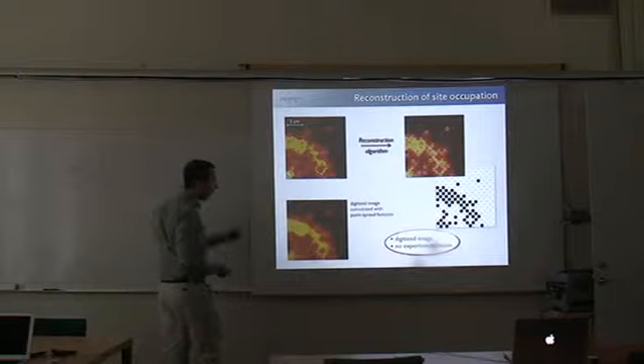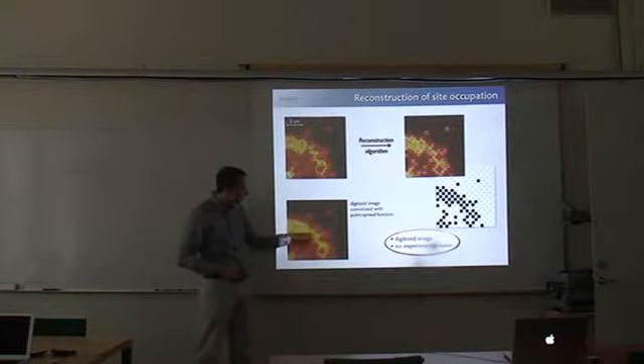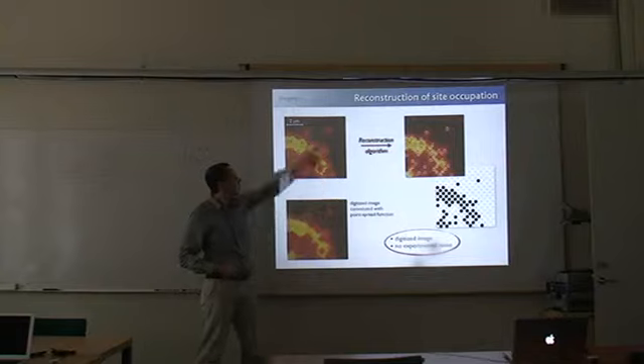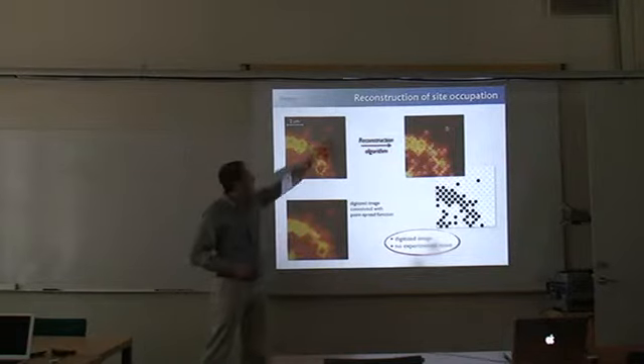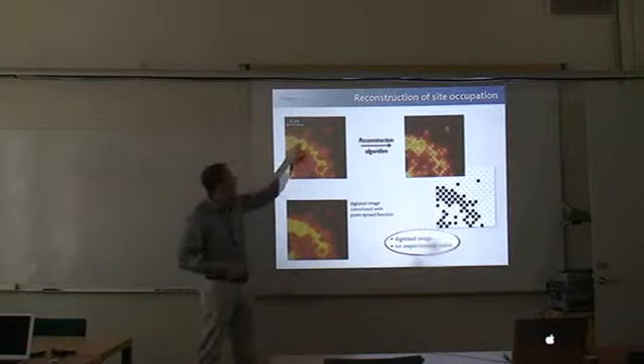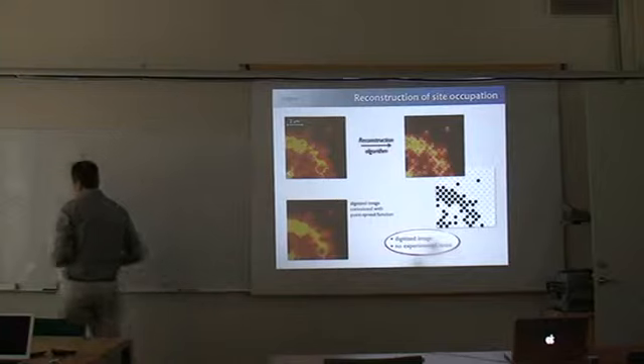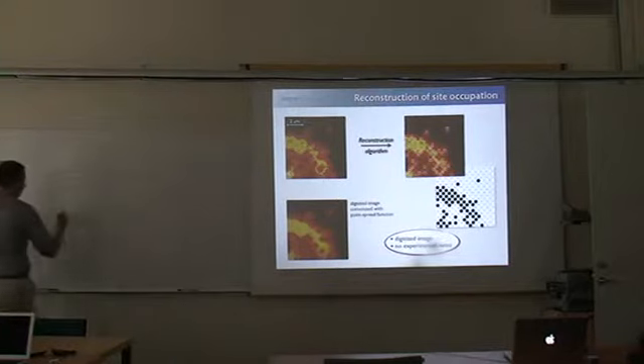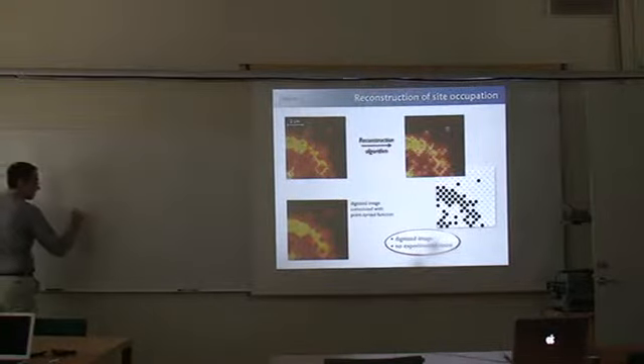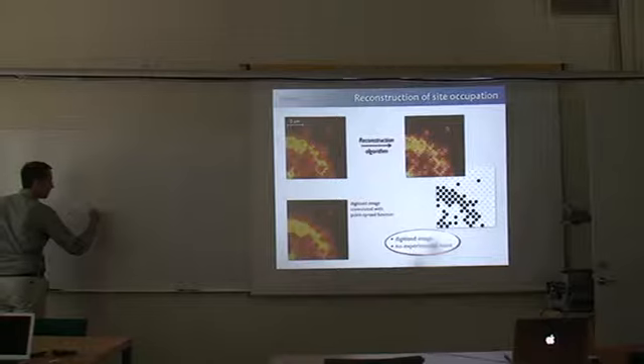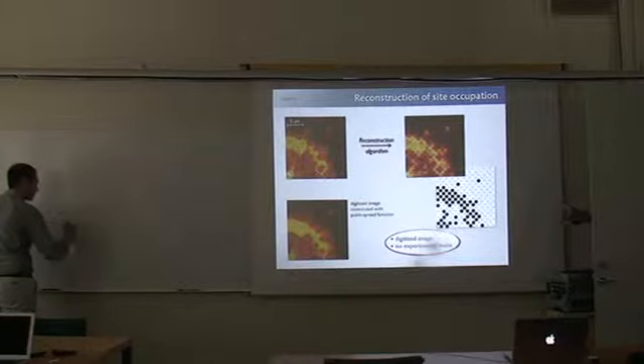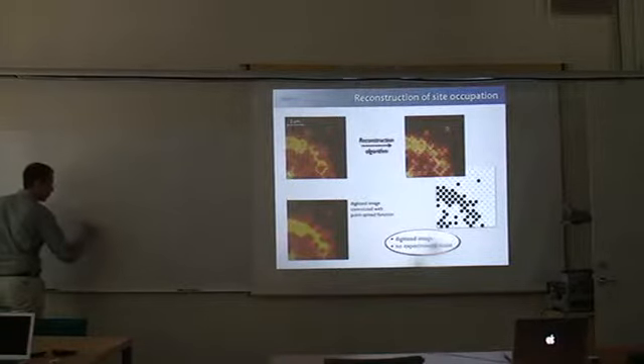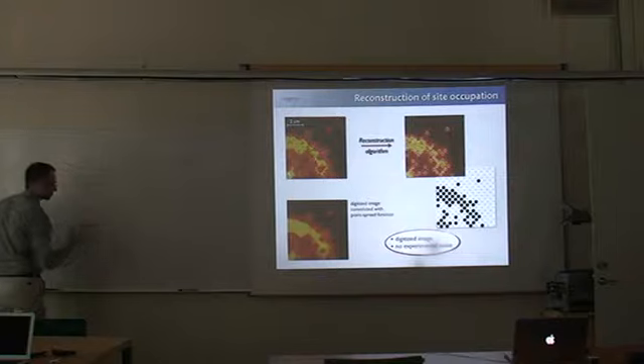What do you say? So this is yellow for a reason. This is a single atom, right? Or this guy here, that's a reconstructed one. This is a single atom. So you're asking, why is this yellow? Well, because our optical resolution is not smaller than the lattice spacing. Our optical resolution is on the order of 700 nanometers. Our lattice spacing is on the order of 532. So you say it's yellow because nearest neighbor sites are overlapping.